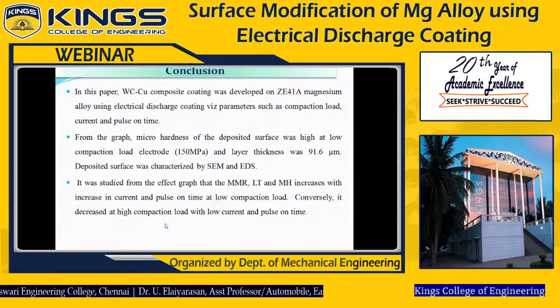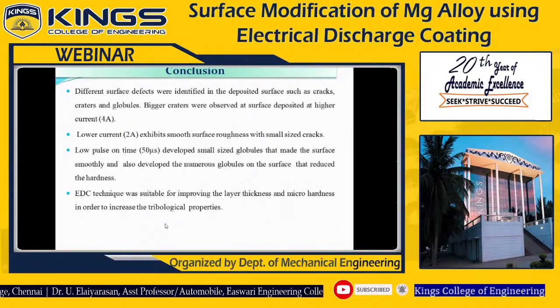It was studied from the effect plot that MMR, LT, and MH increase with increasing current and pulse on time at low compaction load. Conversely, they decreased at high compaction load with low current and pulse on time. Different surface defects have been identified in the SEM image. You can see in the SEM image that several globules, craters, and cracks are observed.